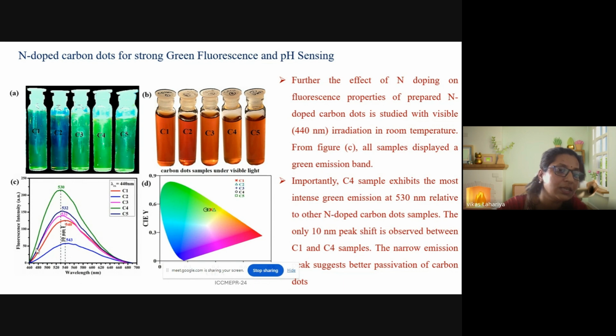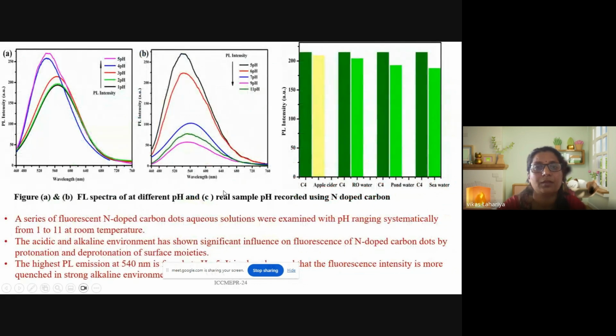This is the green emission at 530 nm, and this green emission is slightly shifted by 10 nm as we change the EDA concentration, and the color is confirmed by the CIE diagram.